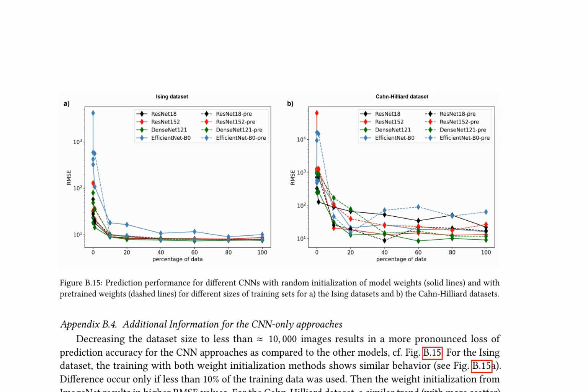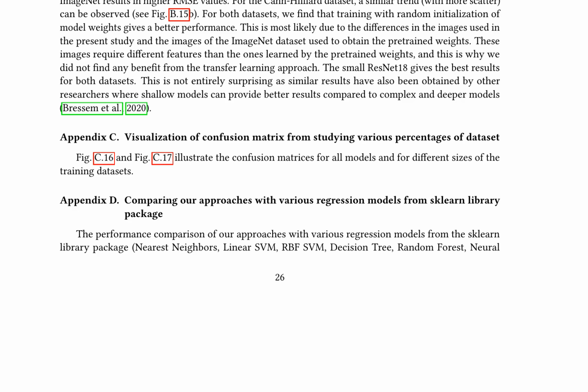Convolutional neural networks, CNNs, with random initialization and pre-trained weights are compared in terms of prediction performance across varying training set sizes for the Ising and Cahn-Hilliard datasets. In the Ising dataset, both weight initialization methods exhibit similar behavior, with differences emerging only when less than 10% of the training data is utilized, resulting in higher root mean square error, RMSE, values with ImageNet pre-trained weights. The Cahn-Hilliard dataset displays a similar trend, albeit with increased scatter. Notably, training with random model weight initialization yields better performance in both datasets, likely due to differences in image features between the present study and the ImageNet dataset used for pre-training.